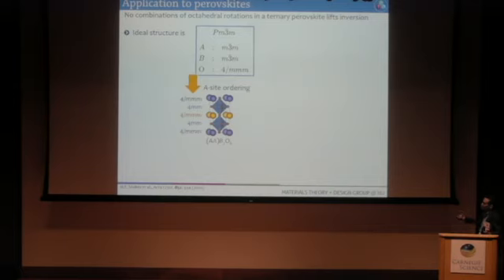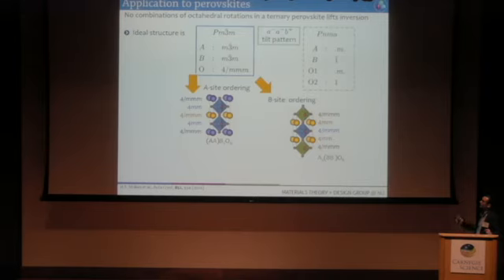I can demonstrate this for perovskite, where we take an ideal perovskite structure. These are the ABO atoms in the structure. This is the site symmetry on those locations. I can add some order. This is A-site ordering. I shift the position of the inversion centers on the A and B sites. I can try B-site ordering. This also shifts the location of the inversion centers. Then I have an added degree of freedom, say the tilt of octahedra. This is a common tilt pattern in perovskite. You can see it maintains inversion symmetry in the structure. This is the tilt pattern.